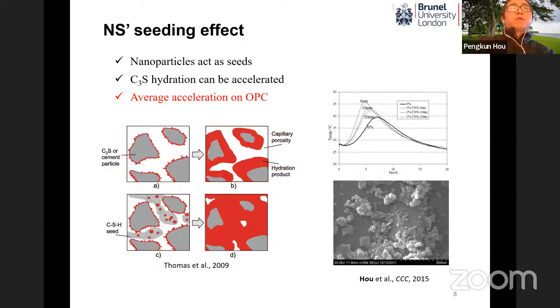When added into cementitious materials, these nanoparticles act as seeds for cement hydration. This has been proven by studying the C3S or silicate systems, where the hydration can be shown to be accelerated. Also, much work has been conducted to study its acceleration effect on OPC. Actually, for OPC it is an average acceleration effect, meaning the silicate phase, aluminum phase, and other phases.